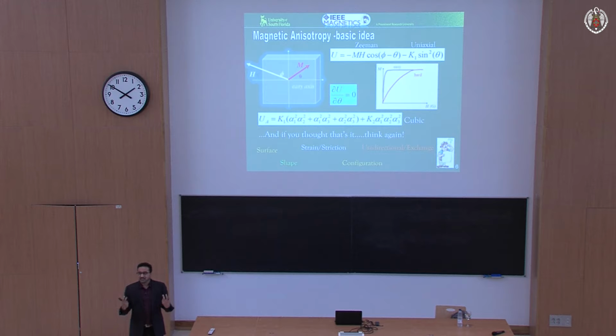You can have nanoparticle clusters that you can make or synthesize, which have different configurations or shapes, and use that as a way to change anisotropy. And last but not the least, exchange coupling, again resulting from interfaces. If you take an antiferromagnet and a ferromagnet, because of the interface, the difference in the anisotropy, you can actually change the shape of the hysteresis loop as well as even move it around. This is the exchange bias.